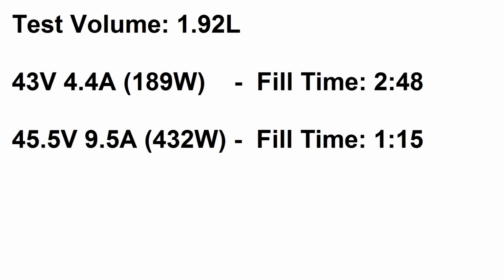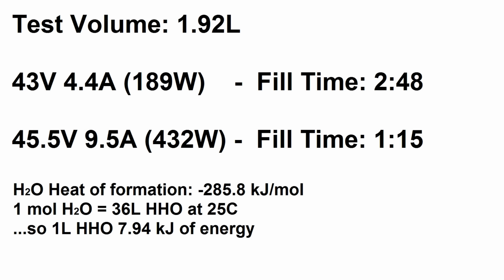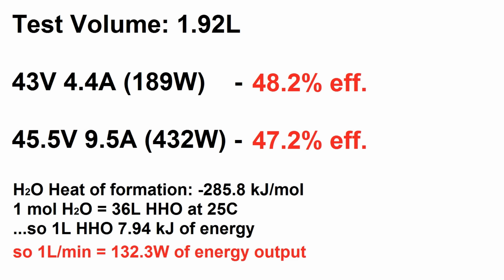At 43 volts and 4.4 amps, it took 2 minutes and 48 seconds to fill the bottle, and at 45.5 volts and 9.5 amps, it took 1 minute and 15 seconds to fill. Working out the chemical energy versus the input power and time, that comes out to 48.2% and 47.2% efficiency, respectively.